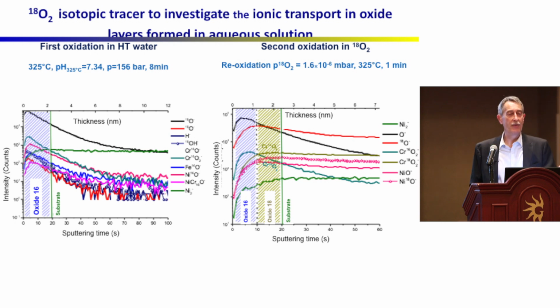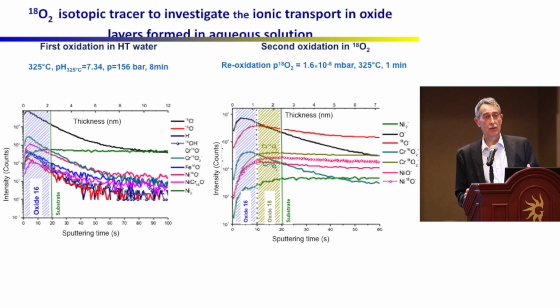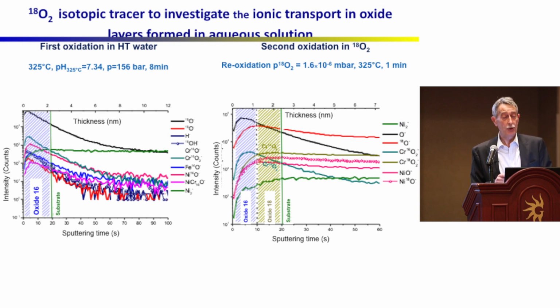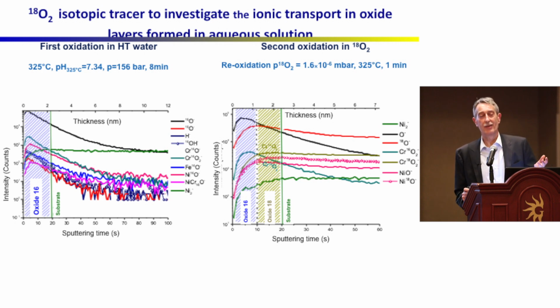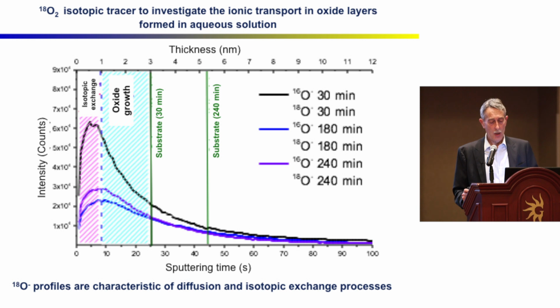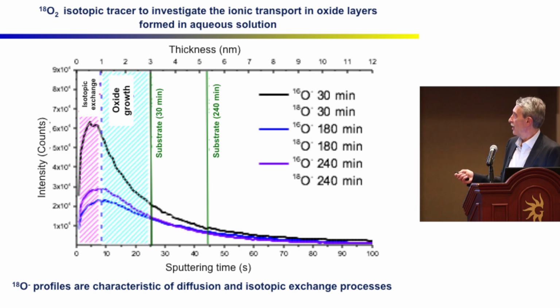So this is a direct evidence that this oxide grows by diffusion of anions, so there are oxygen vacancies. And because this can be shown after a very, very short re-oxidation time of the order of, say, 1 minute, we can reasonably assume that what we are really probing are the defects existing in this oxide when it's in high temperature water.